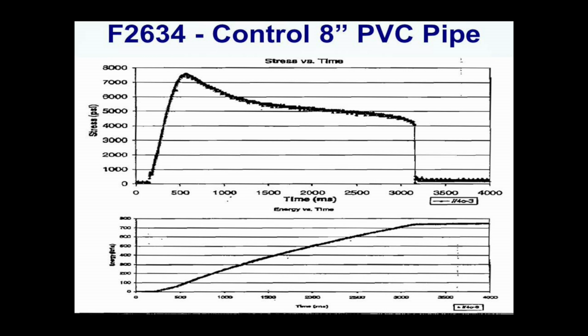This is a typical plot from the report using the ASTM high-speed tensile impact test, for the control 8-inch PVC pipe. This is a plot of stress as a function of time in milliseconds, remembering this is a high-speed tensile impact test. You can see there's a rapid rise and then a gradual decrease.